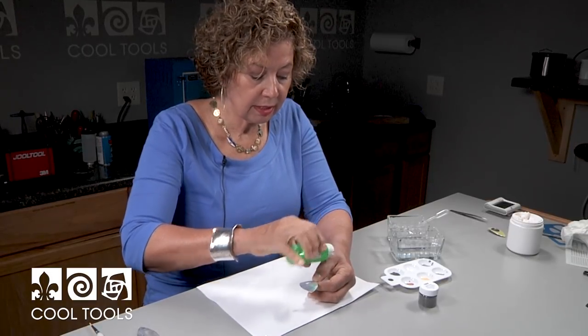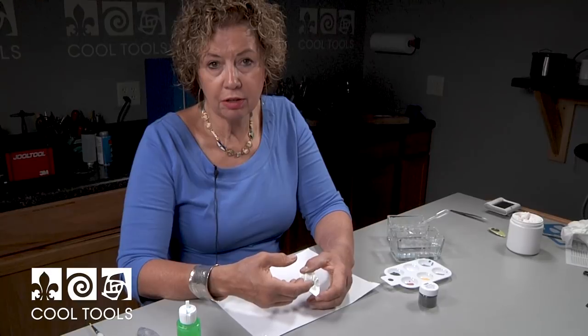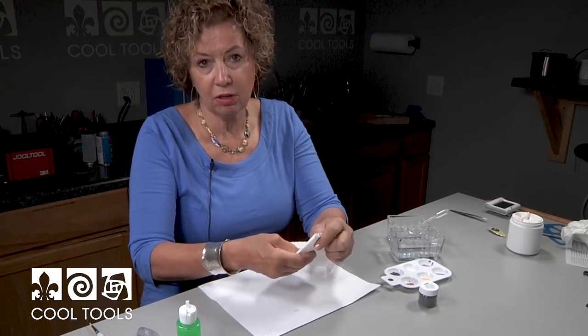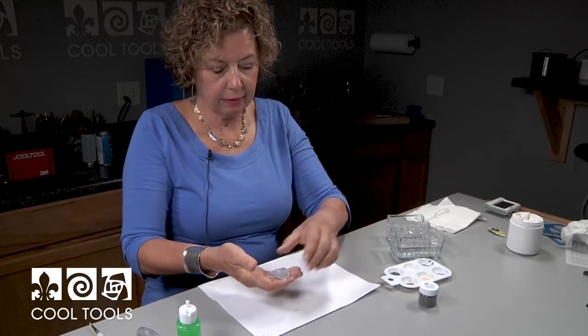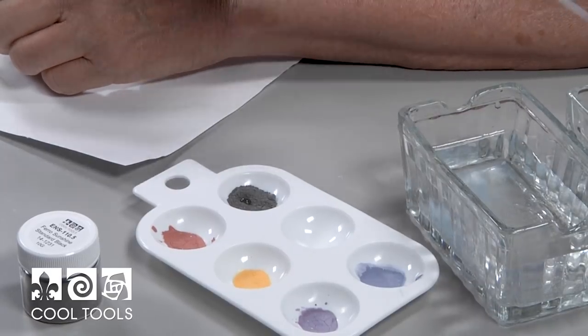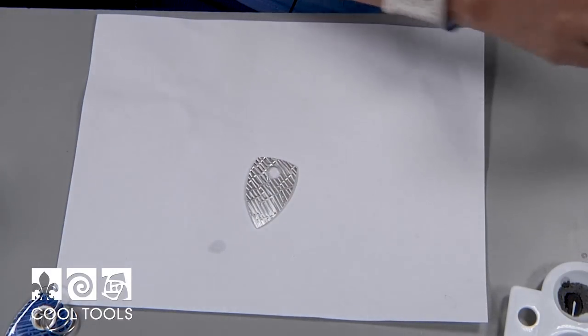Once again I'm using a little surfactant. Somebody asked me, can you put on too much? Oh yeah — if you are adding a lot of foreign ingredients to enamel, you always run the risk of them spoiling the clarity of your piece, and we're working on some expensive pieces of silver. I put just a little on and then I'm going to take a paper towel and wipe it off. You don't need gloves on for this — this is not a dangerous product, it's just surfactant or soap. I have my sunshine color black here in my tray and I'm going to add a little bit of water to it to get it to the right consistency. If I were to put this on the fine silver piece without the surfactant, this black sunshine color would just bead up and it wouldn't fall down into the crevices.